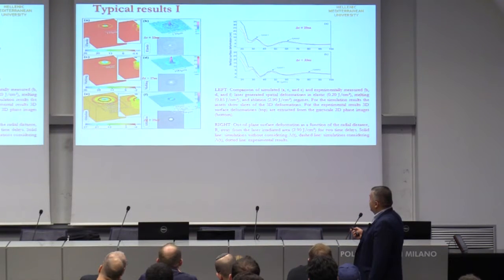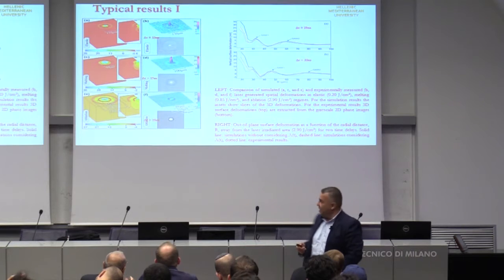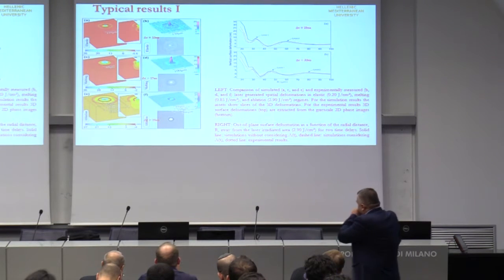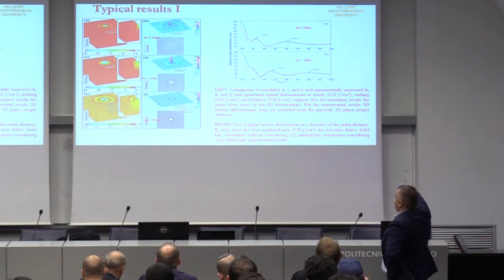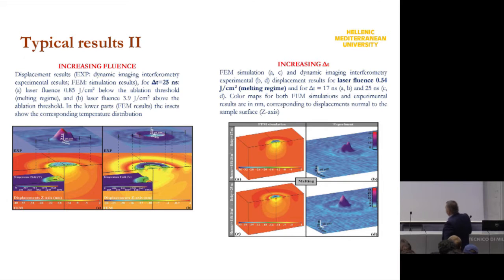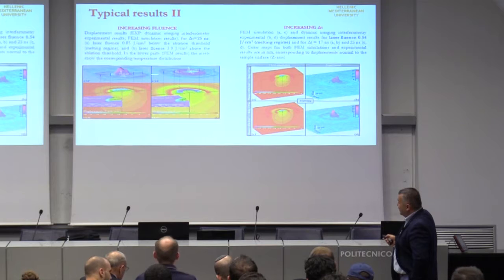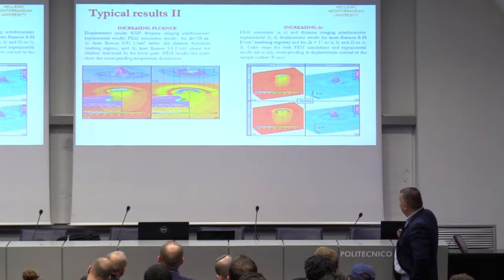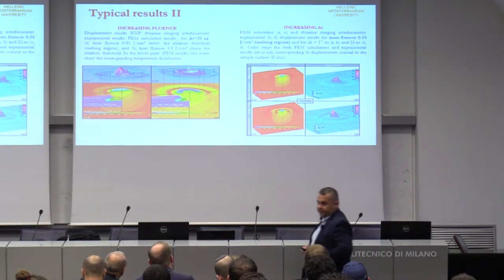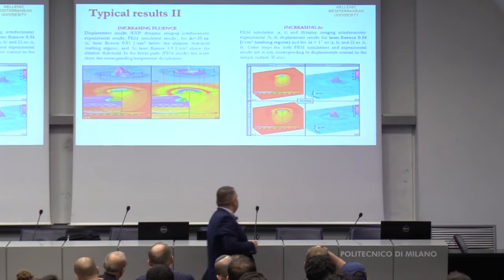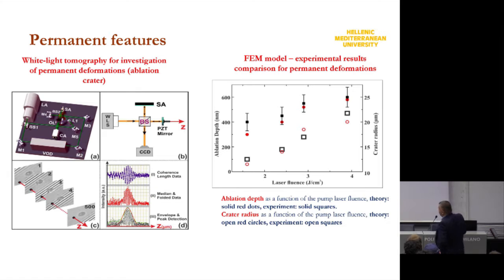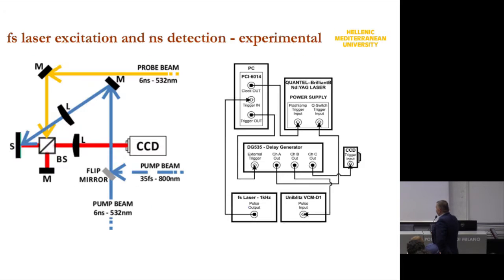And you see here, for example, different delays for different intensities, and you see for example the formation of a crater here, which is an ablation after this delay. Here we are in the elastic regime. There is some fitting of this kind of waves with theory and experiment, and we can explain well this kind of waves. See, for example, these are experimental results, the blue one. And here are experimental results of the surface phase interferograms using this kind of laser. Now, of course, we can test the theory with some permanent features like white light interferometry that we have done in order to see the crater, to see the different structures and things like that produced after the illumination.